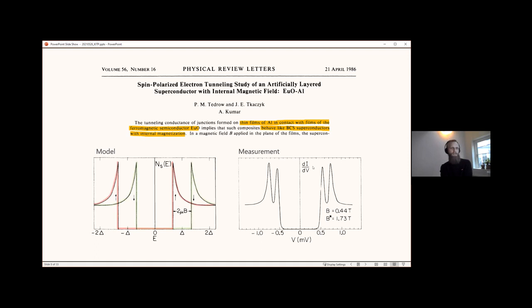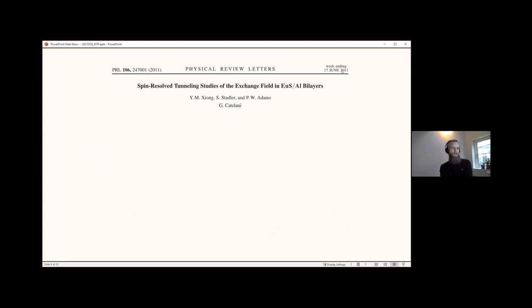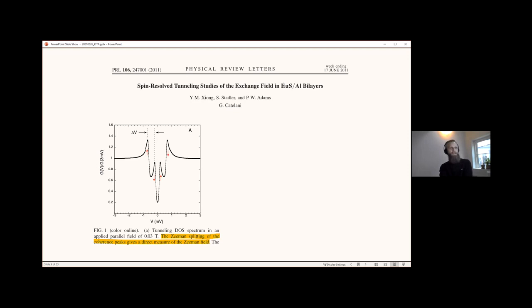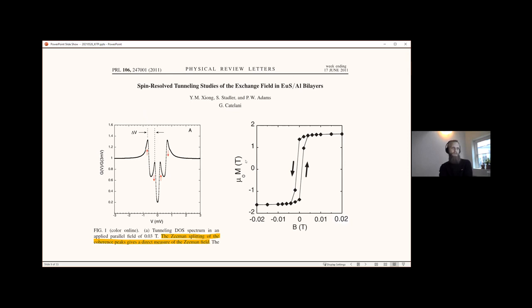Another experiment, slightly more recent, found similar results, but in this case on europium sulfide, not oxide, bilayers together with aluminum. They found that the Zeeman splitting of the coherence peaks gives a direct measure of the Zeeman field, just like argued in the previous work. And by measuring it as a function of magnetic field, they were able to map out the magnetization, or the effective field that the aluminum feels.